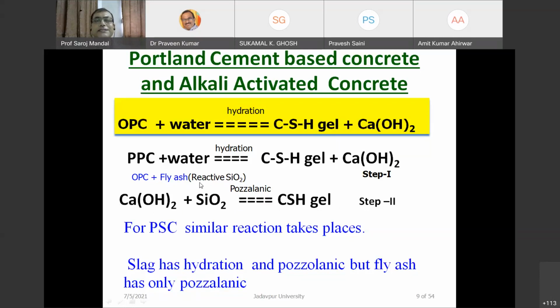And we know that fly ash contains reactive silica and it has no binding material, that means if we add some water into the fly ash, it will not develop any binding product. That is, it does not develop any CSH gel. But on the other hand, slag is a very different material. Slag has both hydration and pozzolanic property, right? That means if we add some water into the slag, it will develop CSH gel and calcium hydroxide, and even the pozzolanic reaction, that is SiO2 present in the slag, will also react with calcium hydroxide to form CSH gel. So slag has both hydration and pozzolanic property. Fly ash has only pozzolanic property, and OPC has only hydration property.